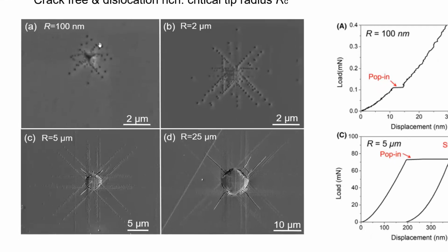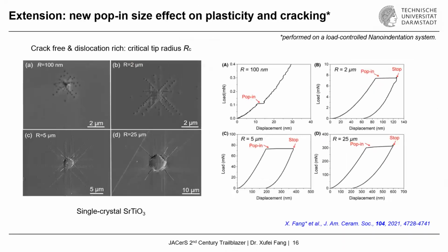The interesting thing is, for the very sharp indenter, as we call it, with the tip radius below 2 micron, we see all the dislocation etch pits here, showing no cracks. But if we look at the 5 micrometer indenter tip and 25 micrometer indenter tip, we see both dislocation etch pits and also cracking. So obviously there is a so-called new pop-in size effect. Depending on the size of the tip, we can either generate a completely plastic deformation, or there is a coexistence of plasticity mediated by dislocations and also cracking.